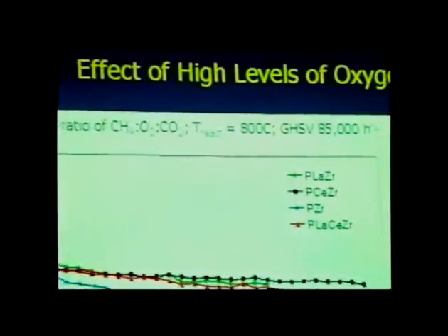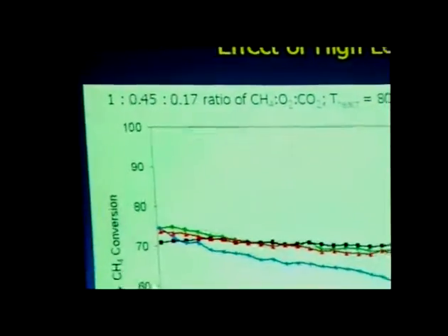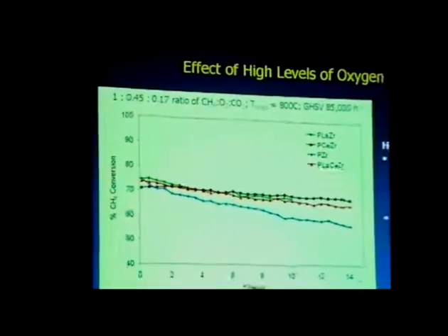If we look at now what happens when we have oxygen in the system, we can see that really there is no distinguishable difference in the activity for all of the promoted materials. However, they still perform better than the unpromoted platinum zirconia catalyst. The hydrogen to CO ratio was high for these materials and constant throughout the experiment.